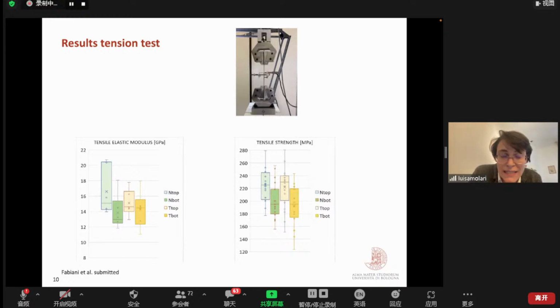The results for the tension test. For the elastic modulus, also in tension, there is not a lot of difference. If we look at the distribution, we do not have a significant difference, and the same for the tensile strengths. Here we can see a slight difference, as was expected, from the bottom to the top. So in the top there is an average value that is higher than on the bottom. But if we compare bottom with bottom and top with top, we do not have significant differences in the strength.